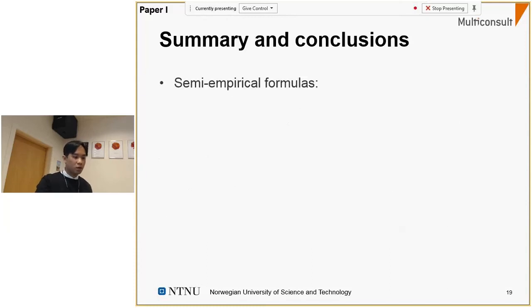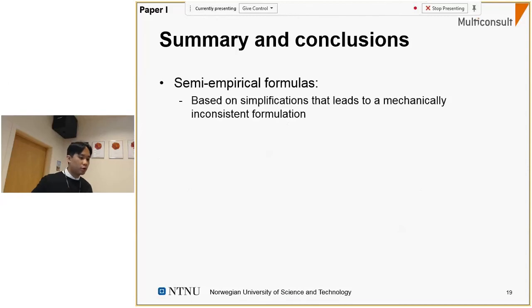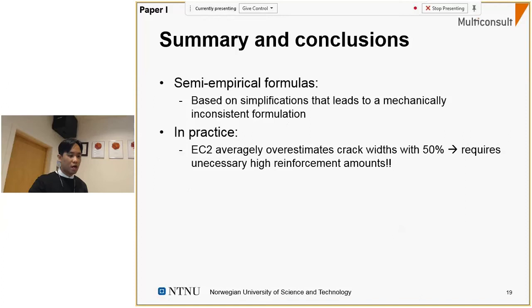So to summarize and conclude the main findings of this paper, the semi-empirical formulas are based on simplifications that lead to a mechanically inconsistent formulation. And in practice, the Eurocode 2 on average overestimates crack widths by 50%. This may require unnecessarily high reinforcement amounts.